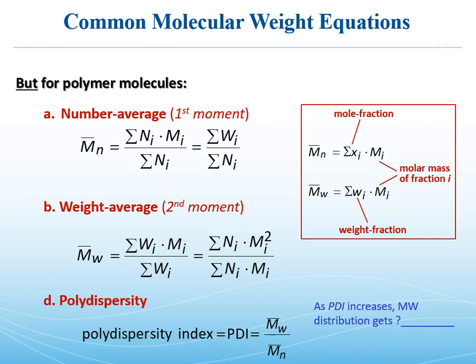You can also get more empirical definitions, such as the viscosity average molecular weight, which is between number and weight average and has to do with a larger molecular weight polymer when it's dissolved basically having a higher hydrodynamic resistance. And that's another way of actually measuring molecular weight. There's a special term for the ratio of weight to number average molecular weight, and that's called polydispersity index. And again, the important thing about that is it's a measure of the breadth, the width of the distribution.